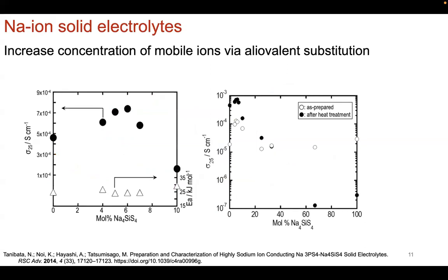Okay, and what we've also seen for sodium ion solid electrolytes is what we've seen for lithium ion solid electrolytes as well, which is that if you have aliovalent substitution, you can also increase ion conductivity. And so that's what you see here in this particular example with Na3PS4 and introducing Na4SiS4. Now, there is a limit to the enhancement of the ion conductivity.